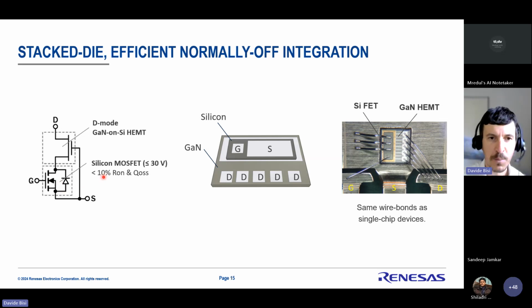is less than 10%. The silicon FET is less than 30 volt, so it's very, very optimized for resistance and capacitance. And the high voltage is all taken by GaN, which is optimized for fast switching with a high mobility channel.